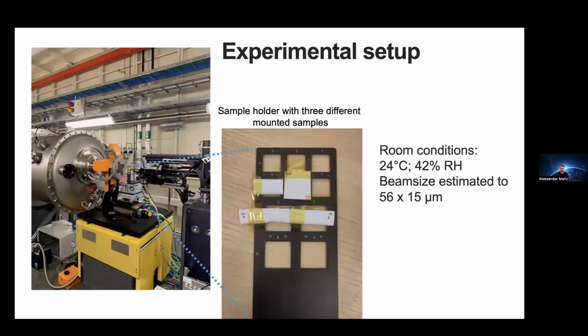So this is how it roughly looked at the beamline. So you have the X-rays coming here from the right, and we have the detector somewhere far away in the tube, and the actual samples are placed on this type of grid, so you can have several samples at the same time. And this particular experiment was done just in ambient conditions, so 24 degrees at the beamline, 42% humidity, so no variation there in this case. And here there are two pieces of the starting material, and then also one piece of an actual straw. So you see here you can mount several samples and then do measurements of them, for instance, consecutively.